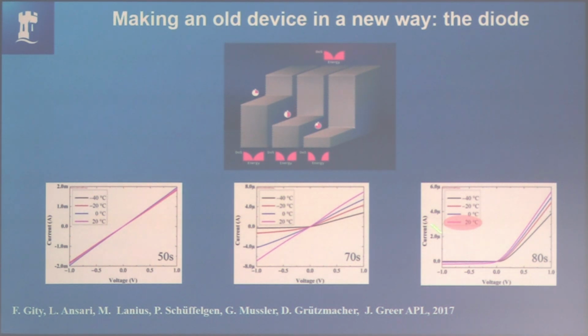And if you etch it for a very long time, and this is a catch, it's only about 4 nanometers thick now, so we're not really sure what we have at the end. But it does look like it rectifies. It's not a good Schottky diode. Matter of fact, it's quite a bad diode from an electronics point of view, which is strange because you would think, since you don't have any interface, it's the same material. The bonding isn't interrupted. You would hope that you would have a very, very clean, nice interface. But there might be other reasons for that, which I will suggest in a minute.